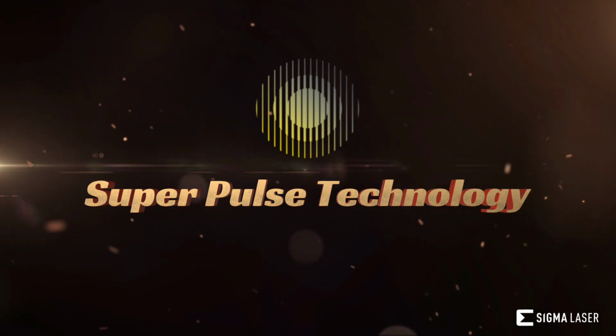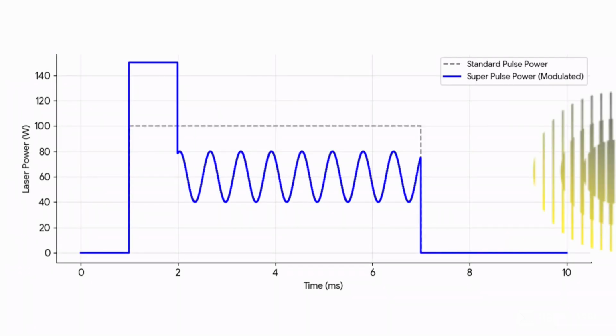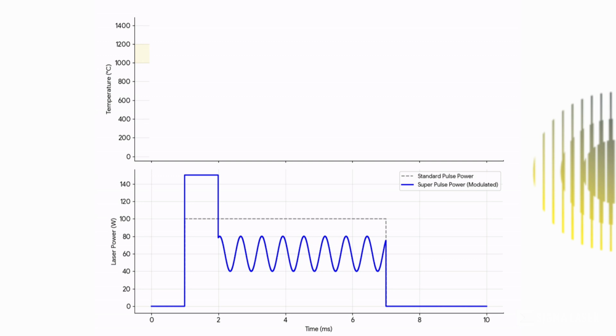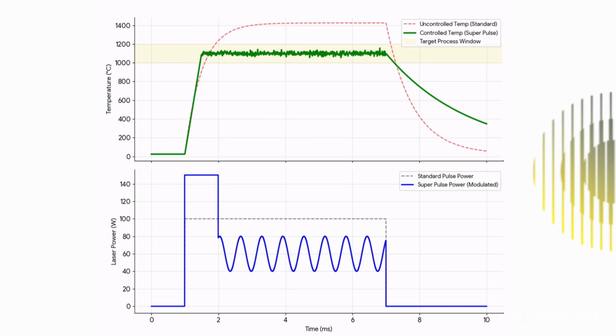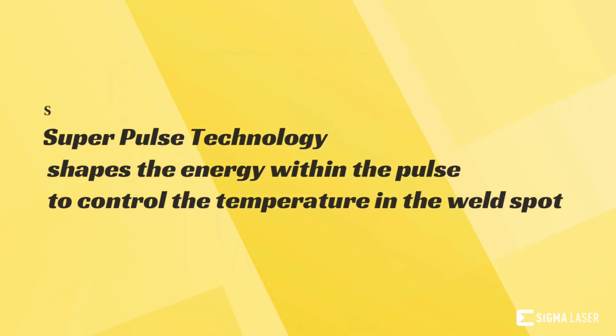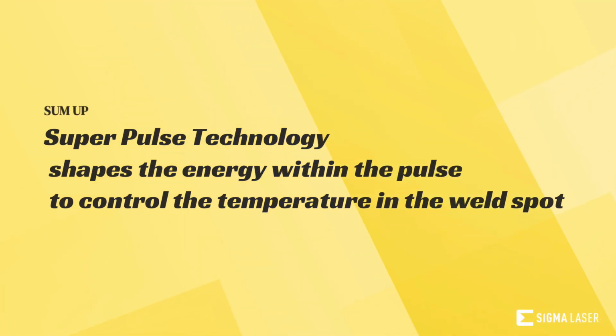Superpulse technology addresses this exact physical limitation, not by increasing power, but by precisely shaping the energy within the pulse duration. The temperature inside the weld spot is actively controlled with microsecond-level temporal resolution. Superpulse technology shapes the energy within the pulse to control the temperature in the weld spot.